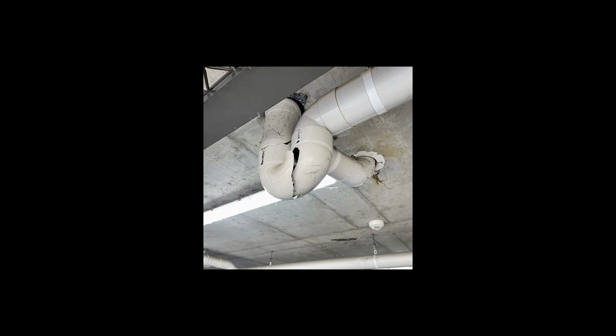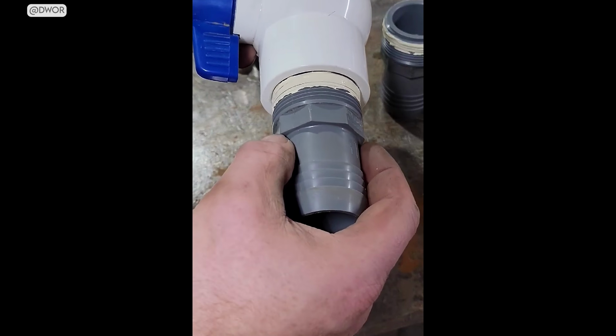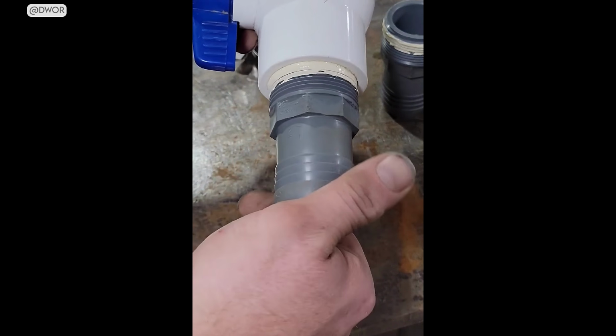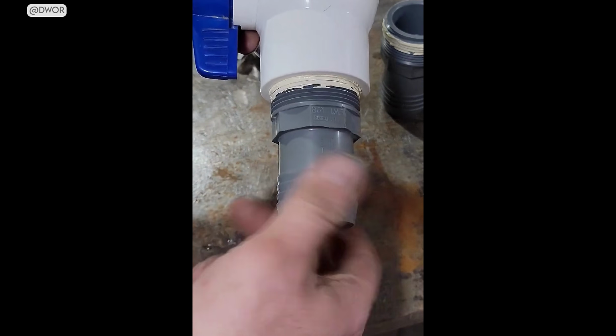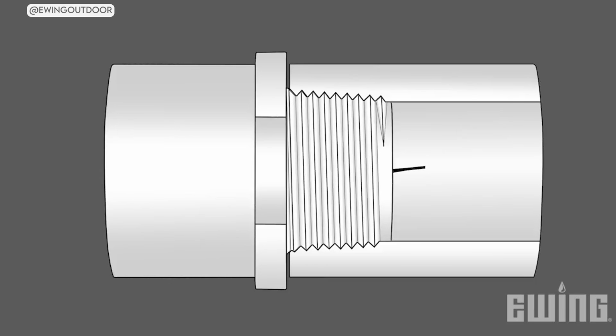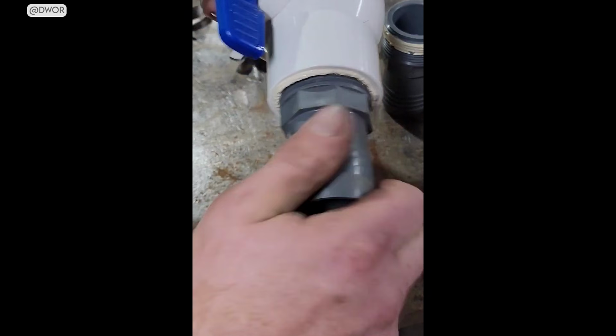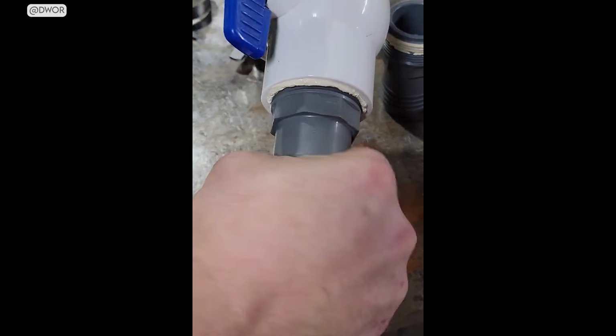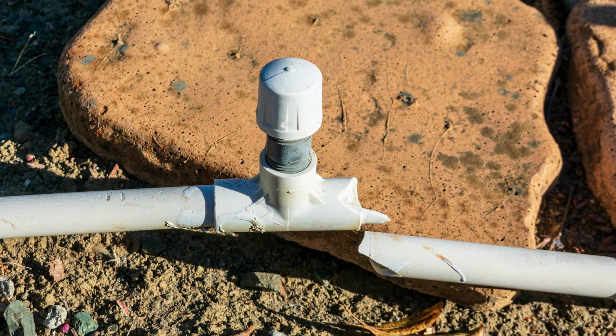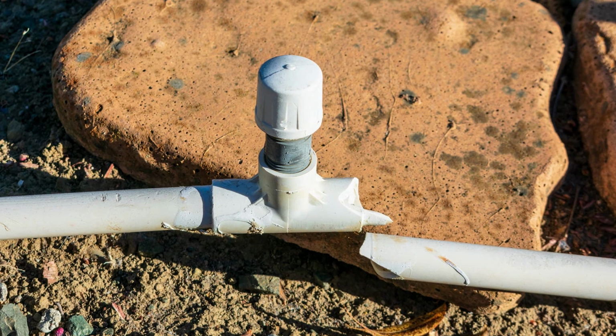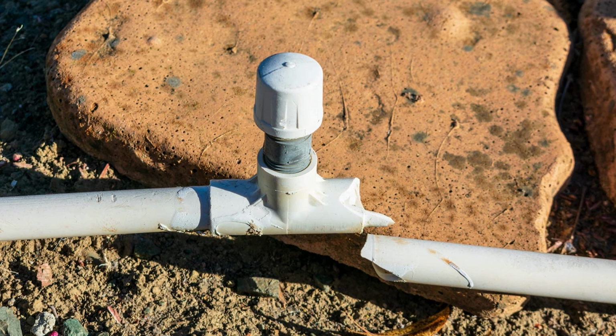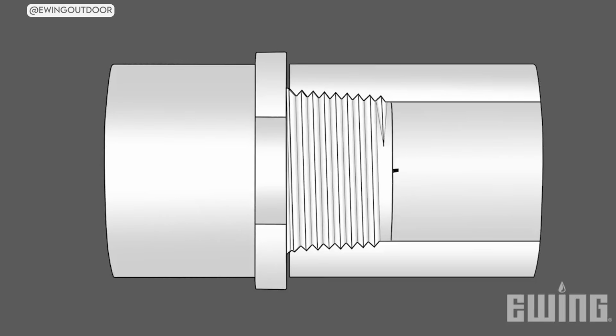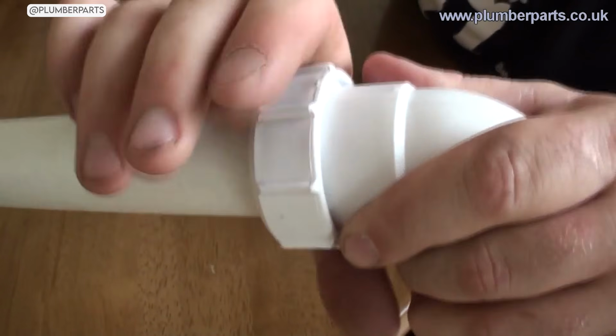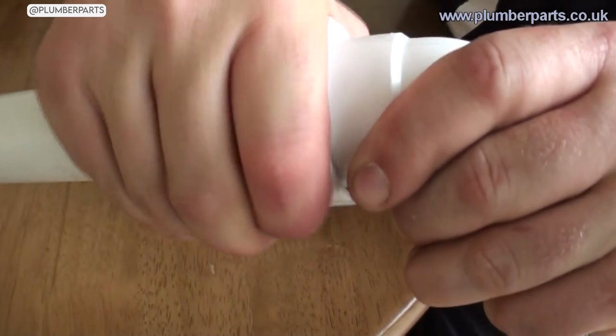PVC absolutely cannot. PVC is a rigid thermoplastic, and when you apply too much rotational force to a threaded fitting, the material does not flex or compress. It cracks internally, and the crack is not always visible to the eye right away. What happens is called stress fracturing. The cracks often begin deep on the inside of the fitting wall, where you cannot see them from any angle. The joint may look perfectly fine from the outside.